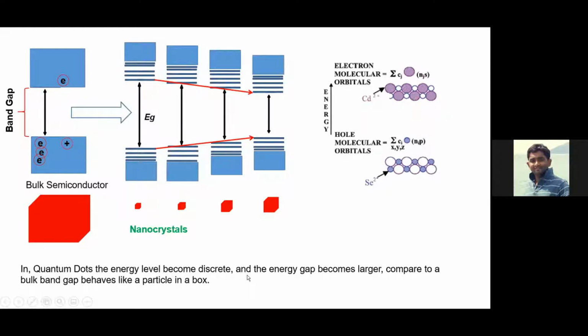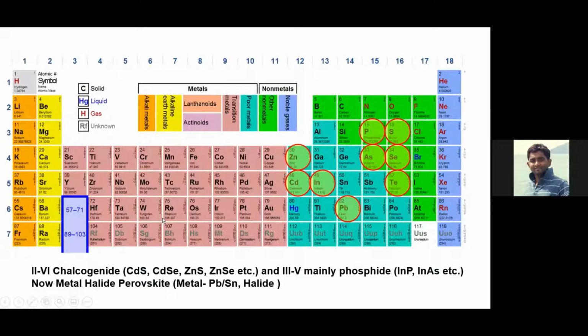Why do I say types? If you see the periodic table here, I will go through the different types of quantum dots. You cannot make quantum dots from all materials. There are plenty of nanocrystals in the literature, but not from every material. Generally, 2,6 chalcogenides like cadmium selenide, cadmium sulfide, zinc sulfide, zinc selenide. So zinc is group 2 here and group 6 here. These two can form a good semiconductor, where we can see very nice emissions and other optical and electronic properties, and also the 3,5, mainly phosphides. People also do arsenides, but the problem is arsenide is toxic, so they don't use it much. But generally indium phosphide and indium arsenide, etc.